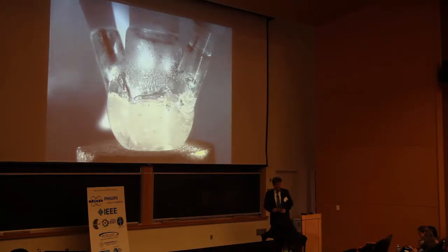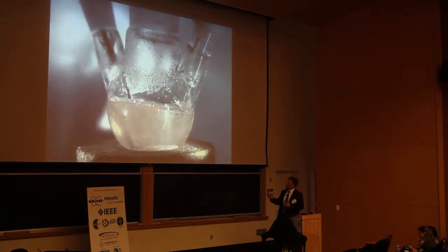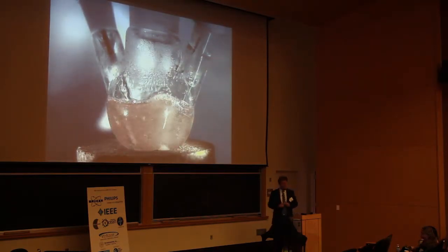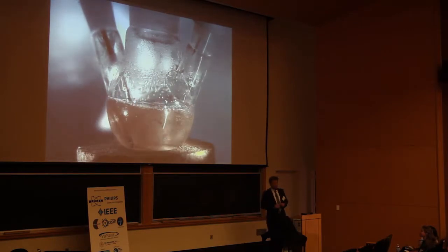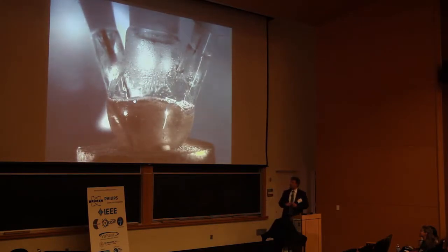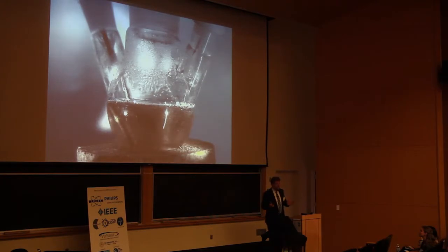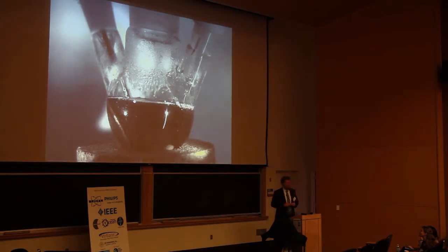And you see you get a very strong initial mixing, mainly because of the injection, not so much because of the stirrer. And straight after the injection, the solution is turning brown. This is the nucleation of the particles. And straight afterwards, so we are still in the very first second, it's starting to get more dark. So the particles start to grow.